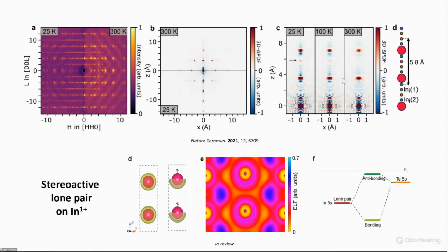But again, why is this happening? The whole point here is a matter that I have studied, and many others have studied: the stereoactive lone pairs in the charge density community. It's sometimes also called metavalent bonding. But the idea here, of course, is that the lone pairs on indium or lead or tin can hybridize with the anion orbitals, and this gives a very strong coupling for electron-phonon coupling, and gives these highly anharmonic systems. But I will not talk more about that.